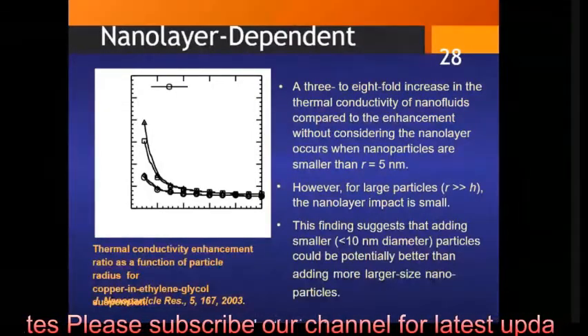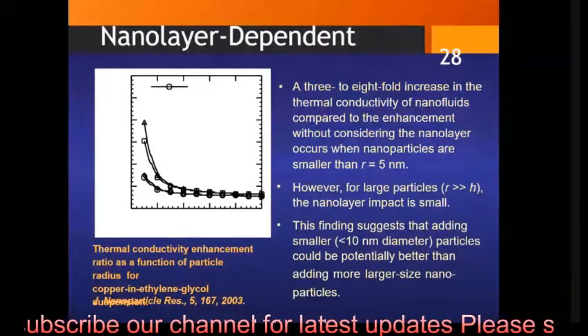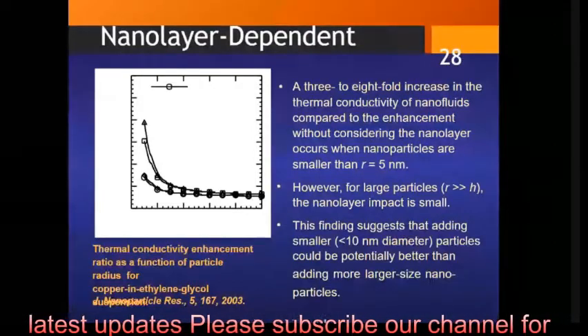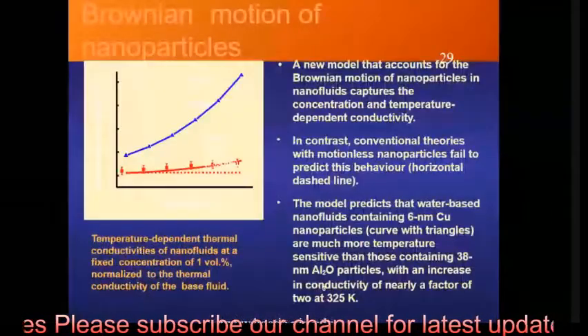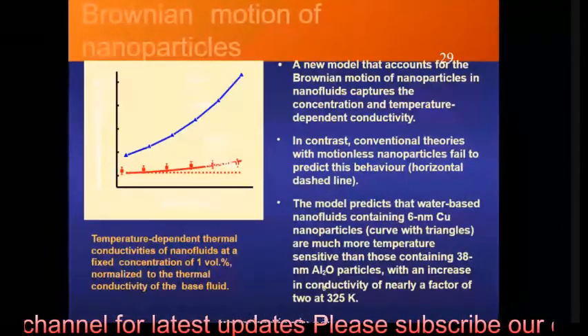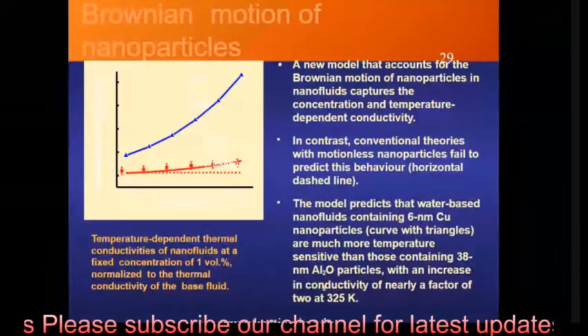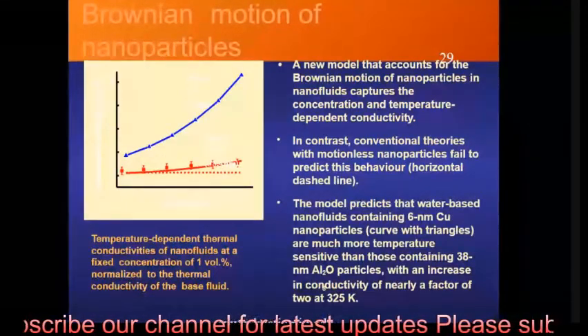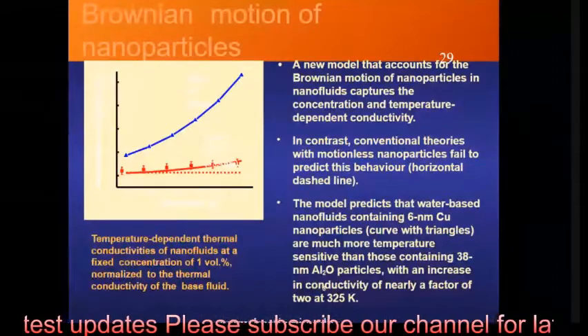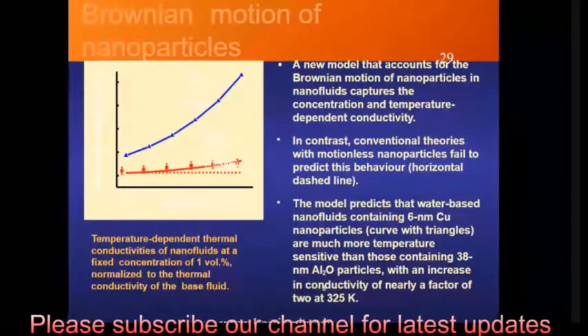For larger particles, the nanolayer impact is comparatively smaller. This finding suggests that adding smaller particles, less than 10 nanometer diameter, could be better than adding larger size nanoparticles. The next one is the Brownian motion of nanoparticles. A new model that accounts for Brownian motion of nanoparticles in nanofluid represents the concentration and temperature dependent conductivity. This model predicts that water-based nanofluids containing 6 nanometer copper nanoparticles, the curve with triangles, are much more temperature sensitive than those containing 38 nanometer Al2O3 particles, with an increase in conductivity of nearly a factor of 2 at 325 Kelvin.